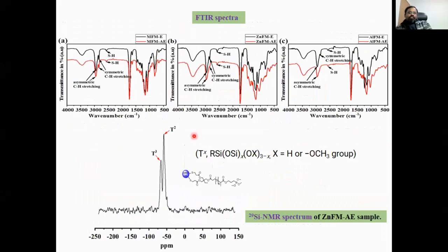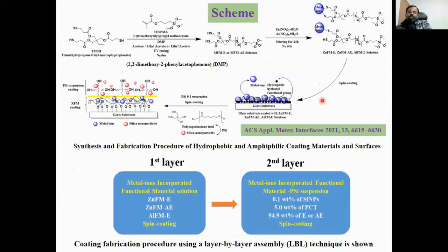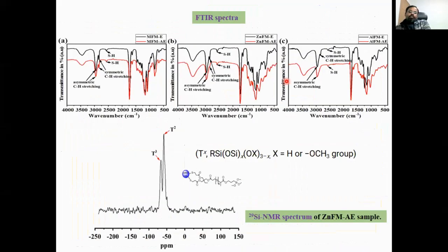And so we checked the functionality of this synthesized material. First, the thiol-ene click reaction modified materials in the presence of both solvents show the mercapto functional group is still remaining, before adding metal ions, just because we used a 1:1 ratio. So the mercapto remains for further reactions. We confirmed that, and after loading with the metal, this peak also still remains, because the reaction is not complete. This makes some full bonding or partial bonding, and during thermal treatment it also makes some S-S bonds, sulfur-sulfur bonds. So this can confirm further.